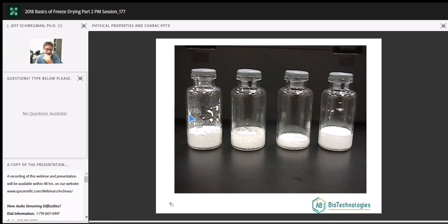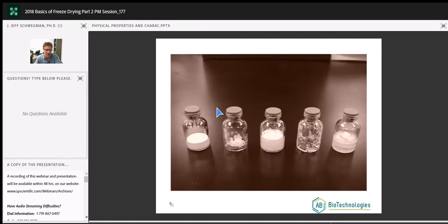Now, the problem here becomes, is this an issue other than being cosmetic? I mean, it looks terrible. And the answer is yes, it could be an issue more than a cosmetic issue. In some cases I've seen, we'll freeze-dry product and we'll get splashing, but while the cake looks good and freeze-dried, the drops on the side of the vial don't freeze-dry and actually collapse. So we've got a nice freeze-dried cake and these sticky globs on the side of the vial. That's not a good situation.